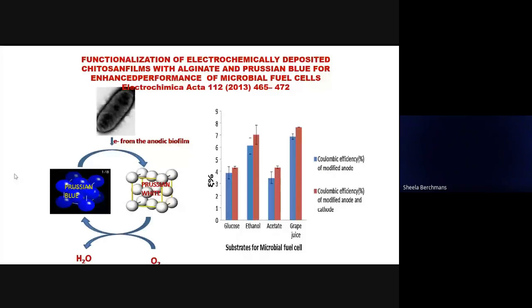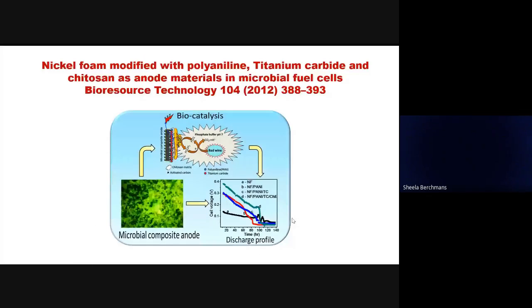Similarly, in the case of ethanol, the current has increased from 10.6 to 67.6. Then also we modified the cathode side. In presence of the anodic film, we modified the cathode side with the Prussian blue so that it enhances oxygen reduction property of the cathode, and we could see how the Coulombic efficiency improved in the presence of the modified cathode. Other type of catalyst we have used are nickel foam modified with polyaniline, titanium carbide, and chitosan as anode material in microbial fuel cells.